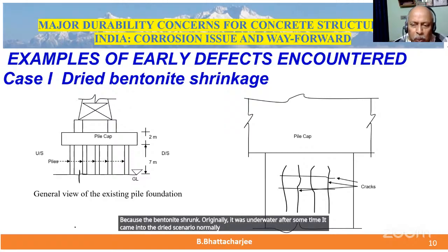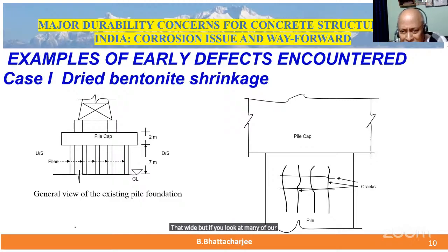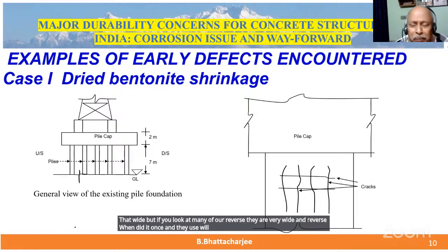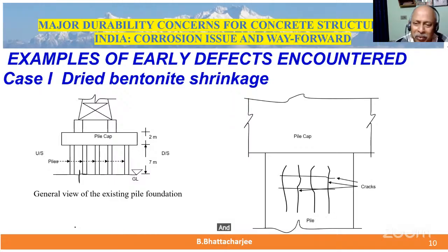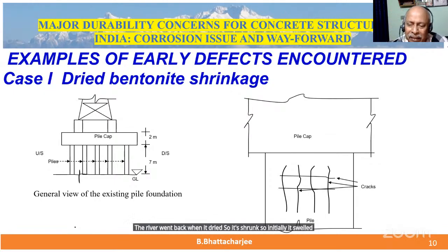Normally, they put well foundations in rivers, the big, wide Indian rivers, Ganges, Brahmaputra, and perhaps not so much the Indus, because in India, the Indus in Ladakh, Leh, is not that wide. But if you look at many of our rivers, they are very wide and quite deep at points, and they use well foundations. This was a pile foundation, originally away from the waterways, but then the river decided to change its course, and obviously it became a wet area. And next time, again, the river went back, and when it dried, it shrunk. So initially it swelled and then shrunk, and that resulted in that cracking.